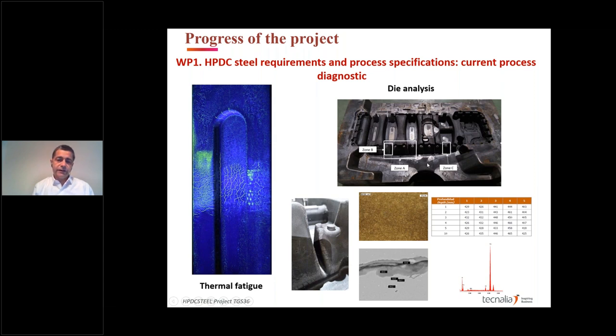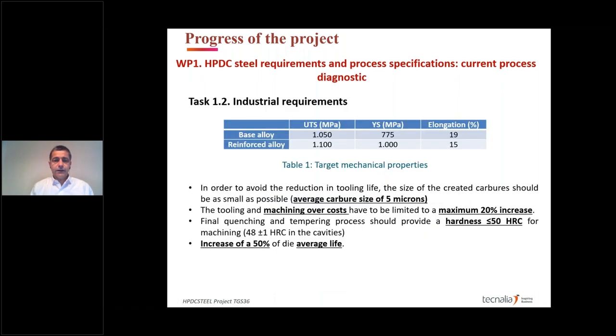So we determined which were the problems, which were the main areas with every area with kind of abrasion or cracking, we have four types of cracking. We put target mechanical properties for the base alloy and the reinforced alloy. We can check here that we increase the mechanical properties, the ultimate tensile strength and yield strength values, because normally if we add ceramic particles, we increase these mechanical properties, but we decrease elongation. That is the key point of reinforcing materials with ceramics.